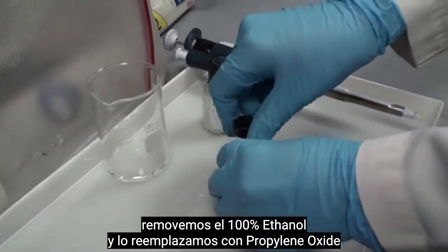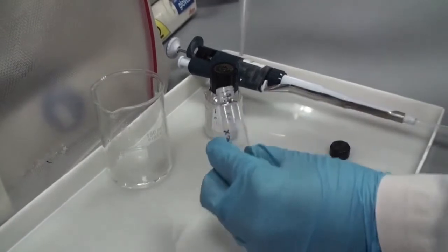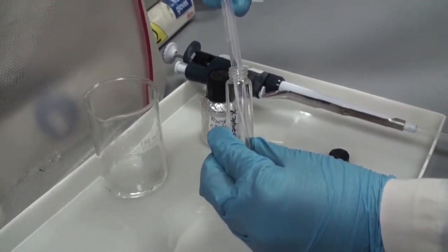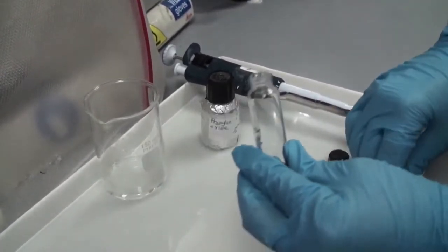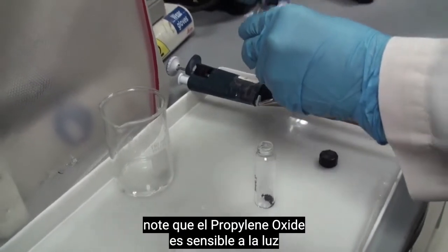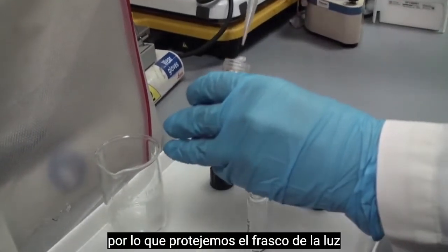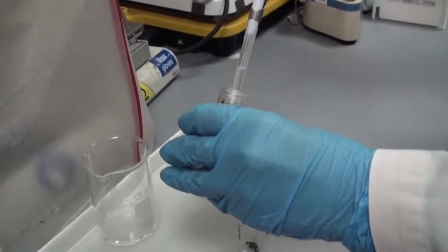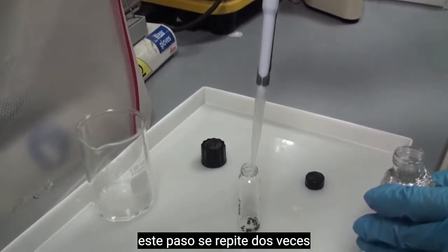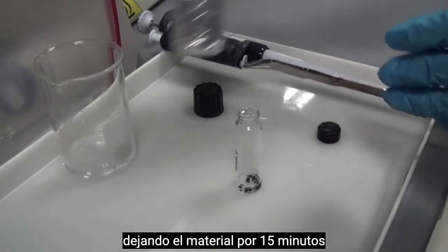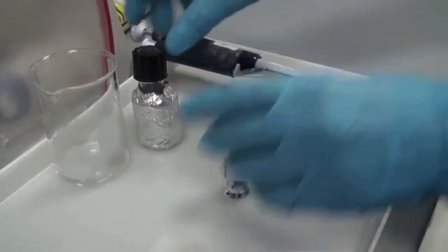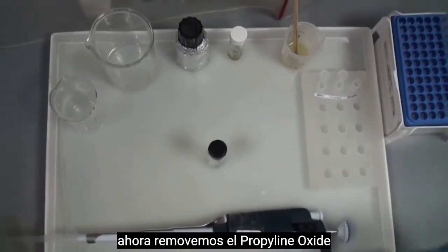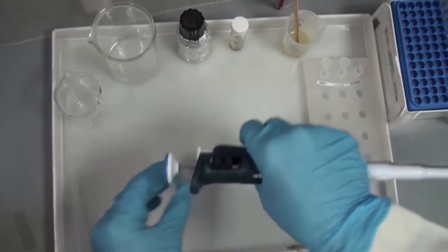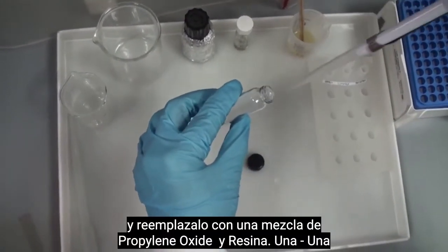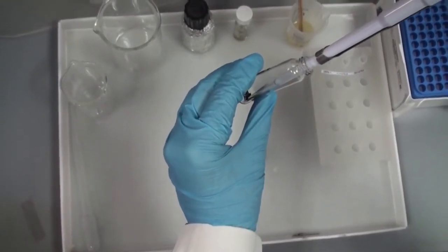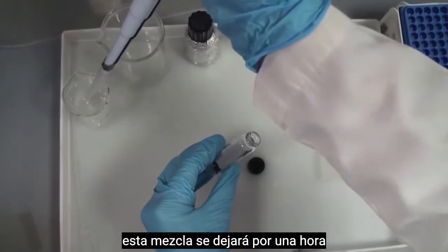We will now remove the 100% ethanol and replace it with propylene oxide. Note that the propylene oxide is light sensitive, so we keep the material shielded from light. This step will be repeated twice, each time leaving the material for 15 minutes. Now we will remove the propylene oxide and replace it with a mixture of propylene oxide and resin, 1:1. This mixture will be left for 1 hour.